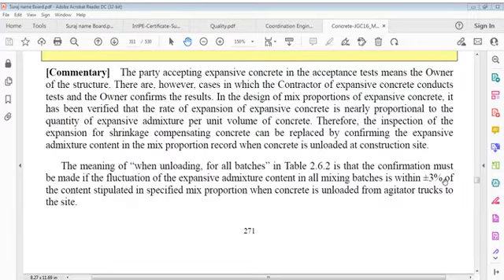In design of mixed proportions of expansive concrete, it has been verified that the rate of expansion of expansive concrete is nearly proportional to the quantity of expansive admixture per unit volume of concrete. Inspection of expansion for shrinkage compensating concrete can be replaced by confirming expansive admixture content in the mixed proportions record when concrete is unloaded at the construction site. The meaning of when unloading for all batches is that confirmation must be made that fluctuation of expansive admixture content in all mixing batches is within plus minus 3% of content stipulated in the specified mix proportion.